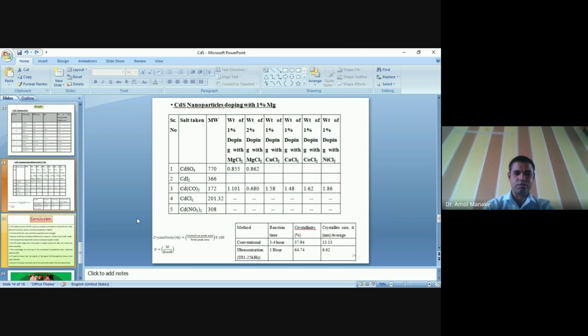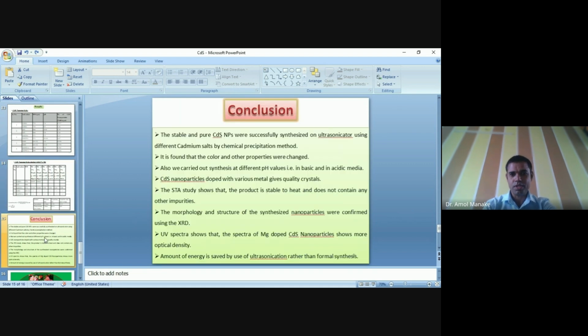From the conventional method, 17.94% crystallinity of the product is obtained, but while using the ultrasonication method, the crystallinity is obtained at 84.74%, and the crystallite size is also reduced while we use the ultrasonication. This is the conclusion. We synthesized stable and pure cadmium sulfide nanoparticles by using the ultrasonicator. It is found that the color and property of the compound is also good.